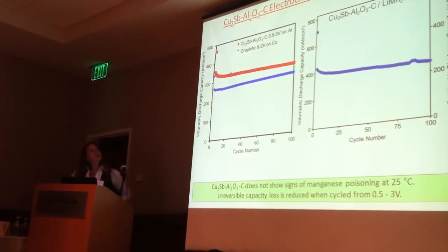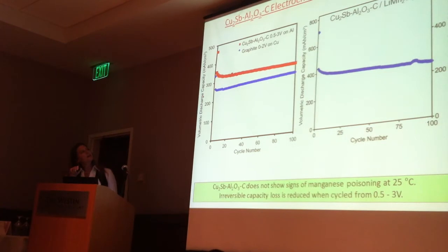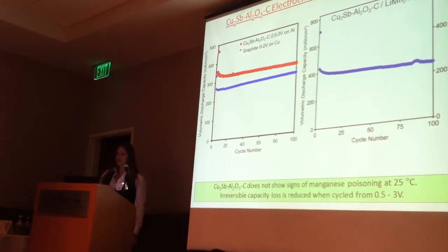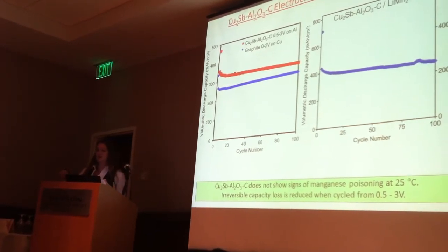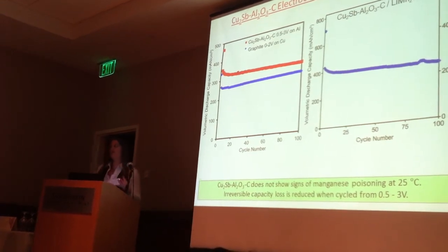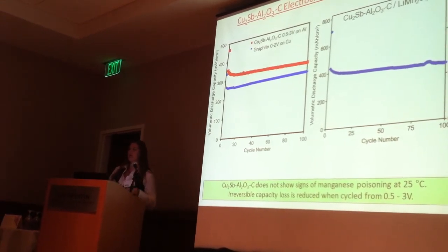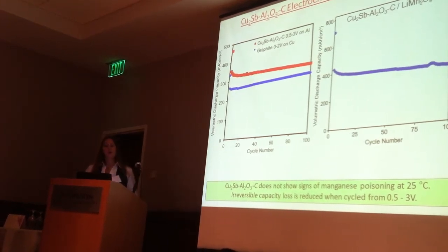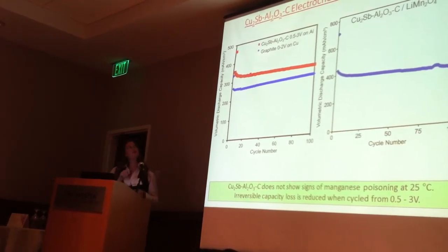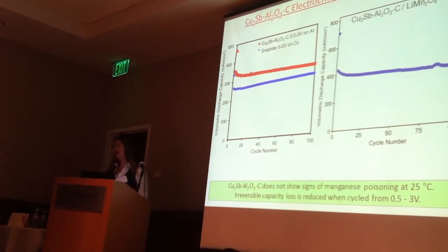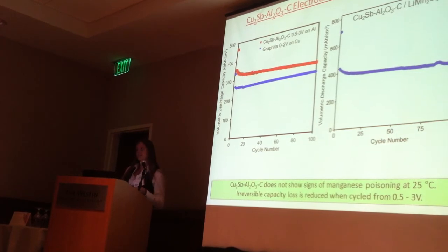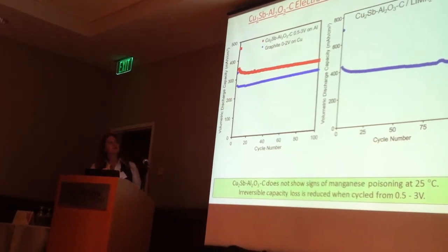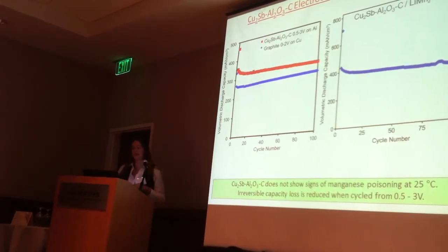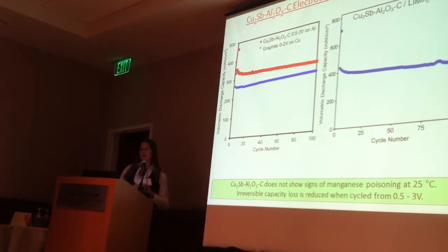We did a little bit of optimization of our material. This red line here is our composite material cycled between 0.5 volts and its open circuit voltage, which in this case was 3. We cycled between 0.5 and 3 so that we could show that we don't have to discharge all the way down to 0 volts versus lithium metal. We can keep it in a safer operating range. What we found also is when we cycled in this range, we were able to reduce the irreversible capacity loss to around 80 to 90 milliamp hours per gram, which was a significant improvement. And this cycle test is still going, but we have 100 cycles of stable capacity, and it's definitely promising with that low irreversible capacity loss in the first cycle.